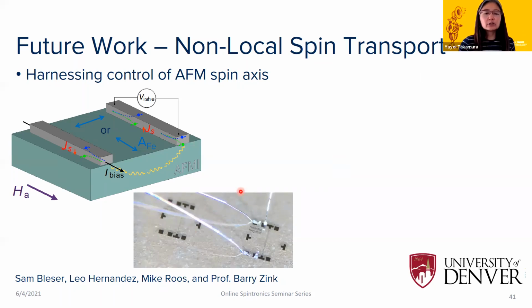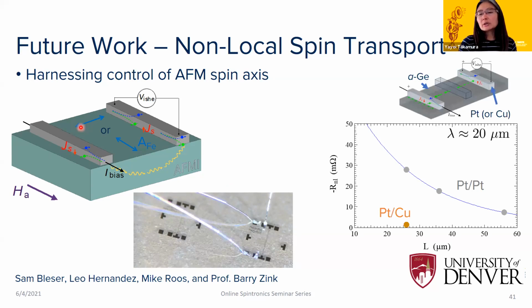I don't want to go into too much detail about the measurements, but the idea is, if we can control the antiferromagnetic spin axis to be parallel or perpendicular to the positions of the axes and the direction of spin flow, can we characterize that anisotropy in the material? This follows on some of the work he's been doing already with amorphous germanium, so it's proving that at least this measurement technique works. And we're working on that now with these complex oxide systems.